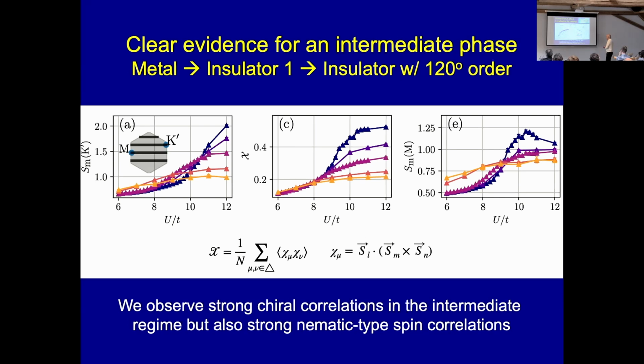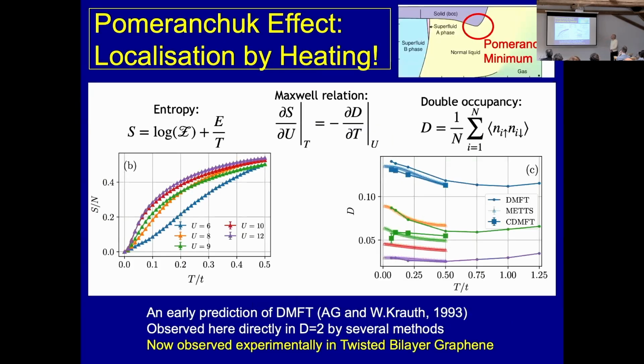Another thing we did in this work, and this is the interest of going to finite T, is we could reveal in this two-dimensional system the famous Pomeranchuk effect, which is actually an early prediction of single-site DMFT from like 30 years ago. Pomeranchuk effect is the fact that you can make a liquid become a solid by heating, which is a remarkable phenomenon, due to the fact that the solid, or the localized Mott state, has more entropy than the liquid. We showed this from single-site DMFT many decades ago, and this is present in this triangular lattice Hubbard model. This is also realized experimentally in TBG (twisted bilayer graphene).